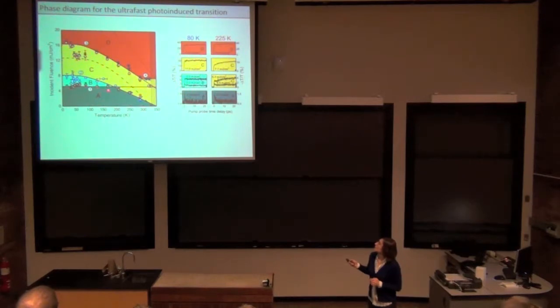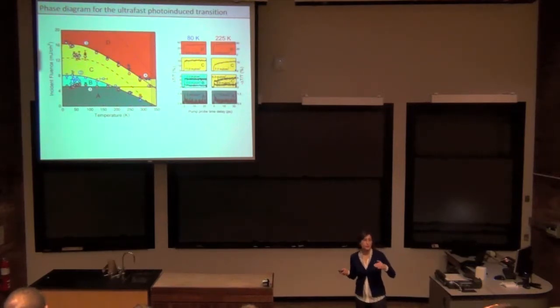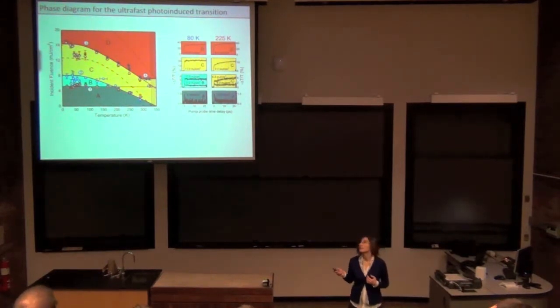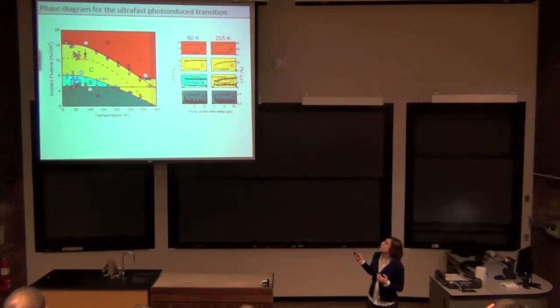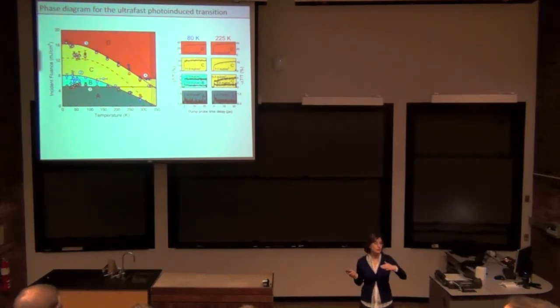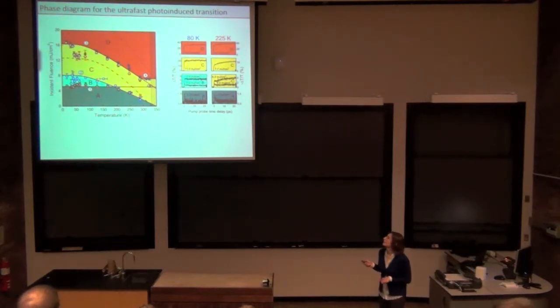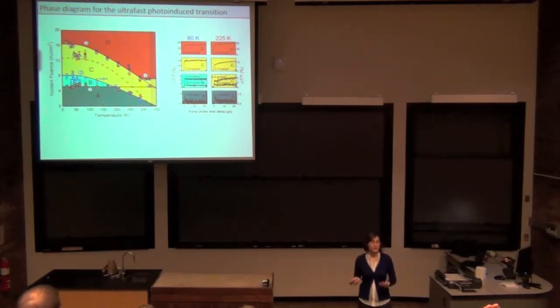So these symbols here are almost completely overlapping. They're the thresholds for achieving this metallic state at 5 and 25 picoseconds. Then these circles are the threshold for the slow rise behavior at higher fluences. Then these symbols over here, again almost overlapped, are for achieving the full metallic state, about 34% modulation in transmission, at either 5 or 25 picoseconds after excitation. So, okay, we have this phase diagram. What does it all mean?